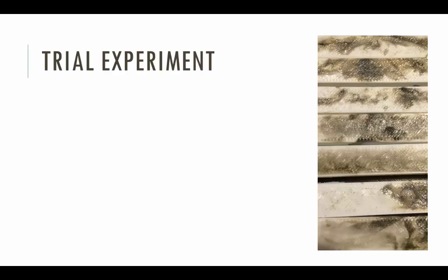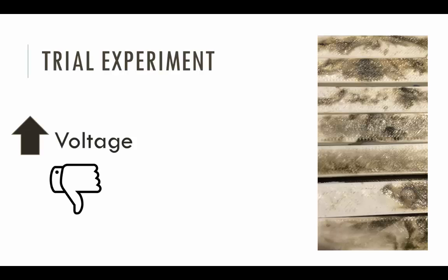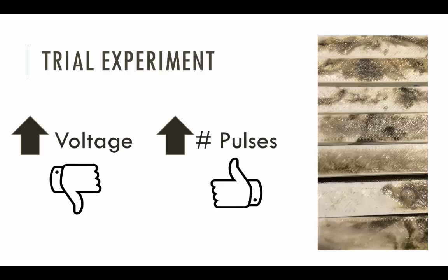As we look on the slide, you can see these prints that we have here. These images were white when I began the experiment, and the dark spots are pretty much burn marks on the surface of the print. The key takeaways from this experiment were that contamination of oils and inks on the surface increases the likelihood of burns occurring. A high voltage causes burns on the surface, and a high number of pulses coupled with low voltage creates a smooth surface on the part.